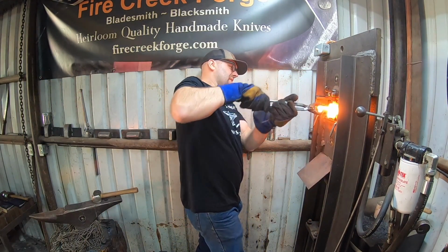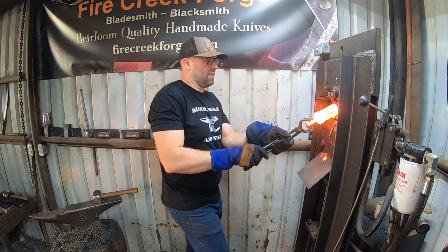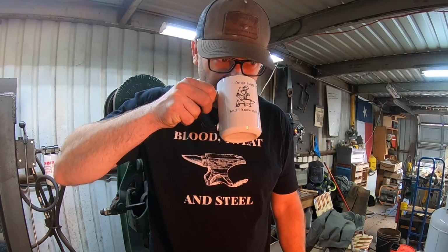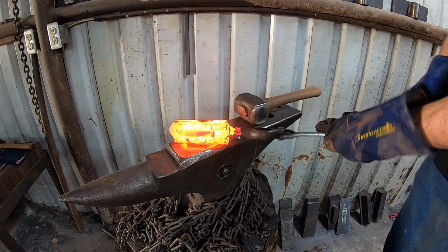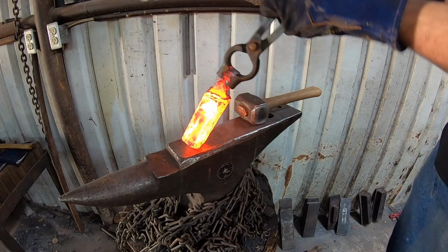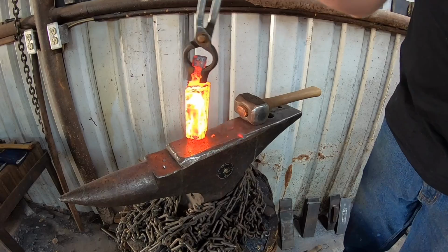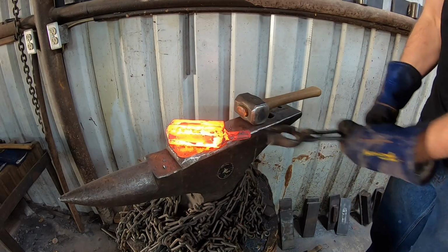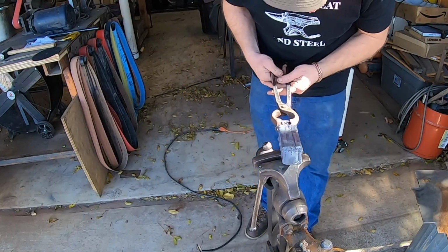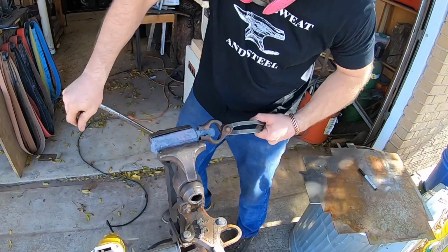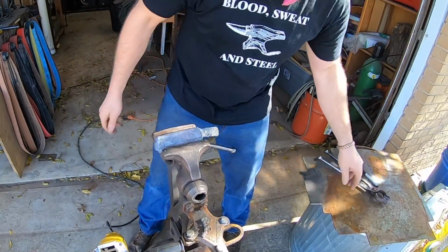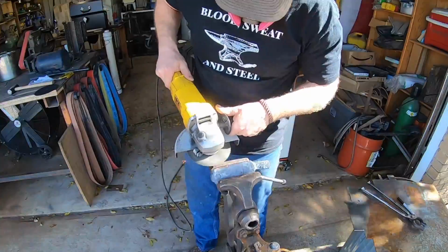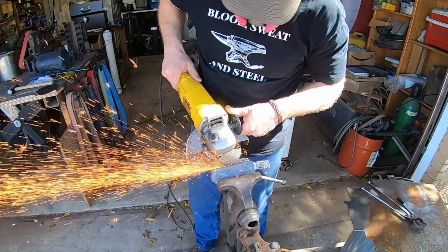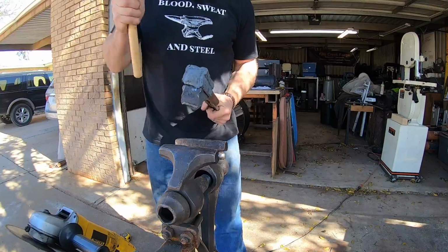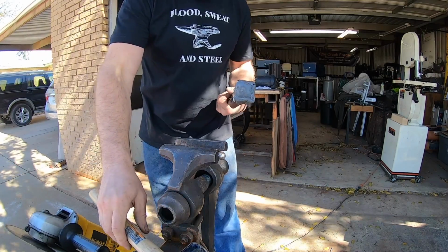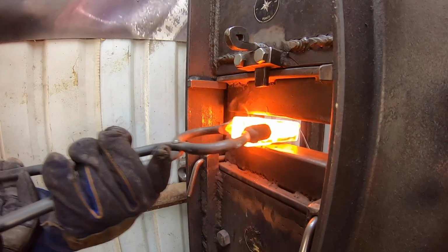I'm completing the forge welding process multiple times to try to make sure that we have a good solid billet before we move on. There's our finished forge welded billet. Let that cool down a little bit, and then we can start cutting the jacket or the canister off of the billet. This should come right off. That white paint has titanium dioxide in it, which creates a non-welding barrier, and with a few cuts here and there, it comes right out.